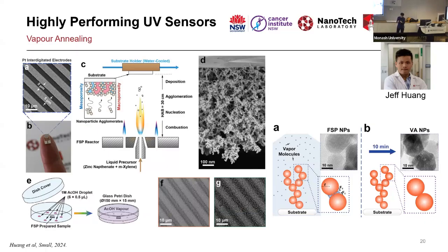But in terms of the ethanol droplet, yes. When we make the film bigger, like this size, we had to do 10 droplets all around. Then we realized that the middle one is still not being impacted. So we put in a syringe pump, and instead of putting a droplet, we very slowly feed it. It didn't work. We're still trying. This is what happened about 2 months ago, even though the first paper was published 2 years ago. We still have problems with the scalability of the ethanol droplet.